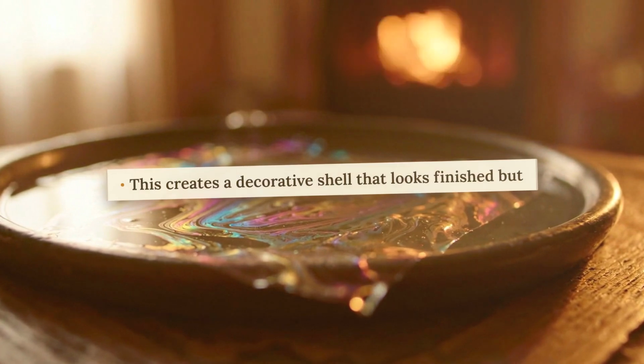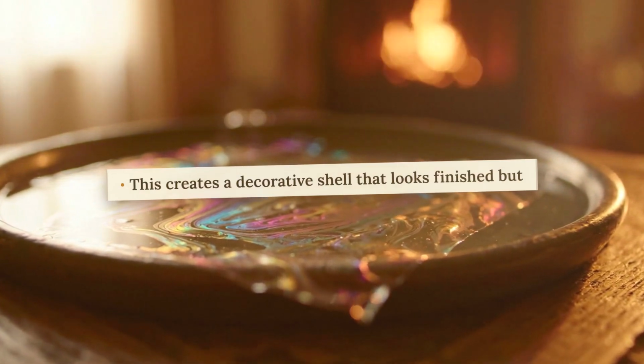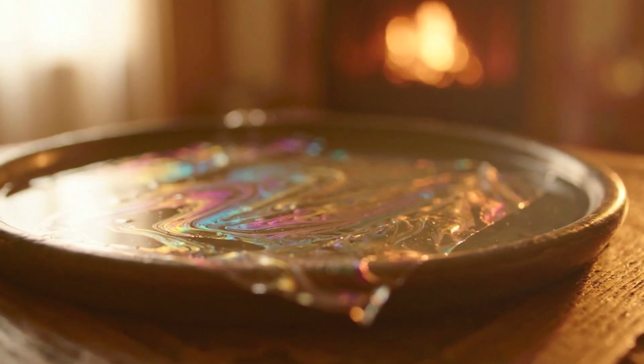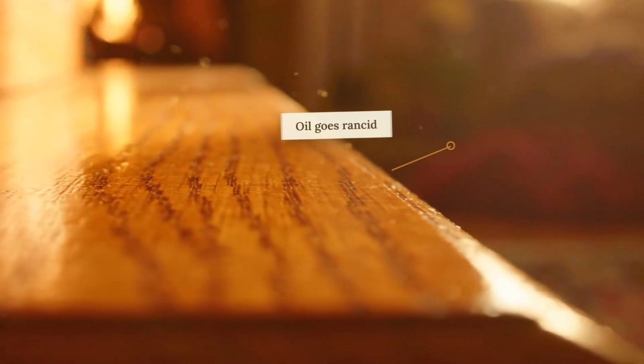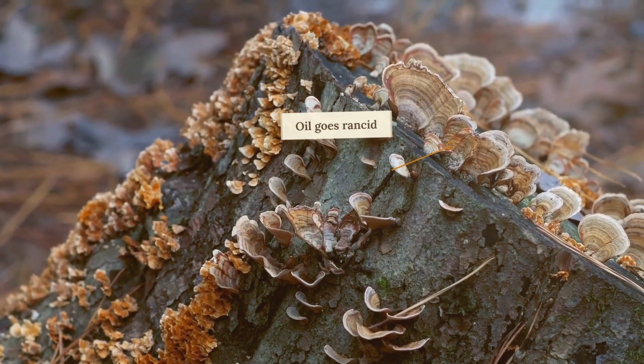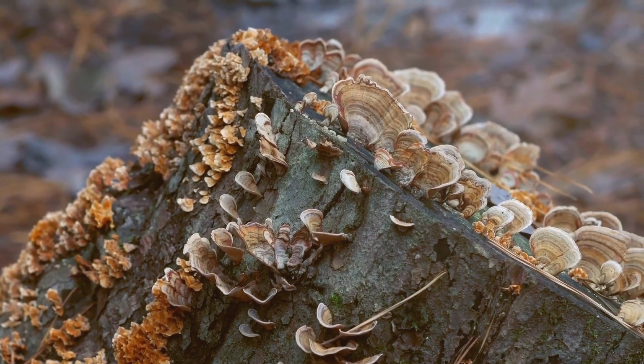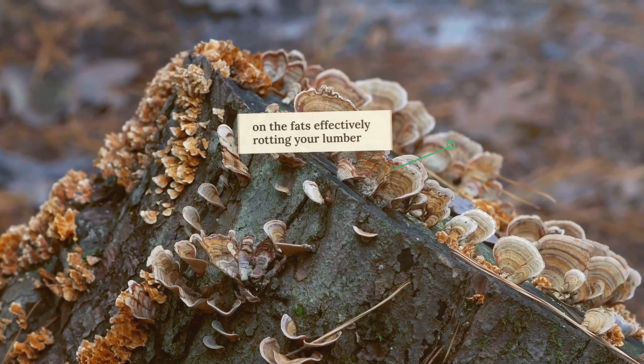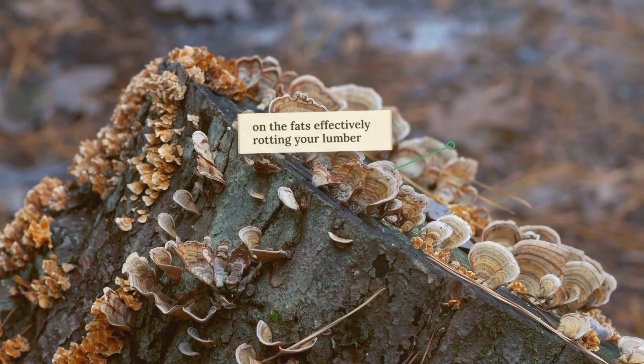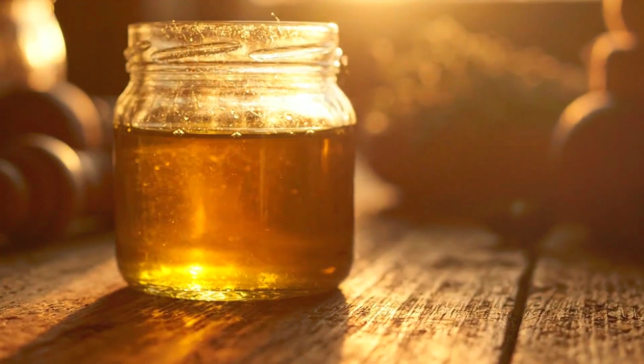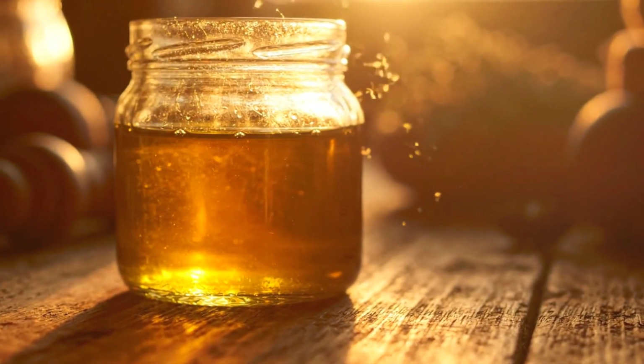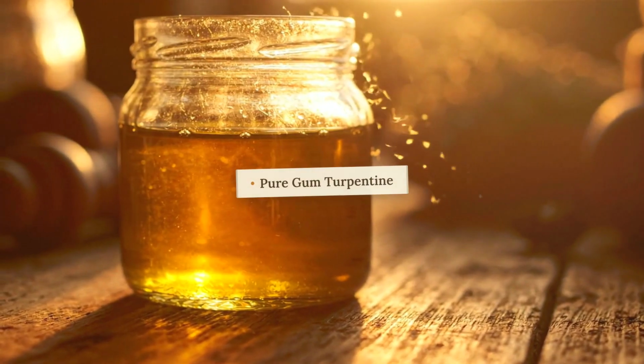These metallic dryers cause the surface of the oil to skin over almost instantly. This creates a decorative shell that looks finished but leaves the oil deep inside the grain in a liquid, unpolymerized state. Over the next 3 years, that trapped liquid oil will go rancid, attracting specific types of mold that feed on the fats, effectively rotting your lumber from the inside out while the surface looks perfectly fine.